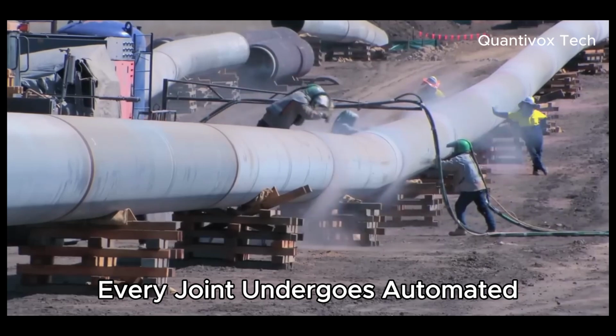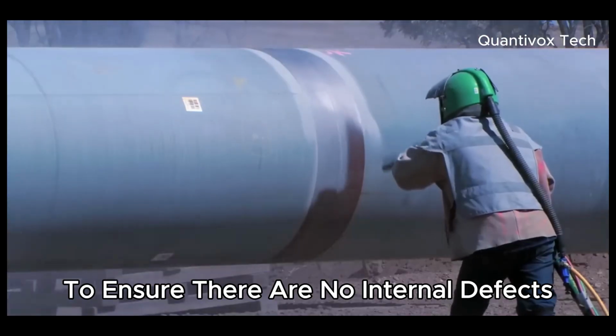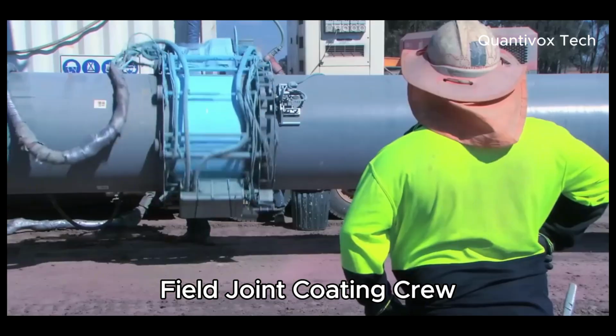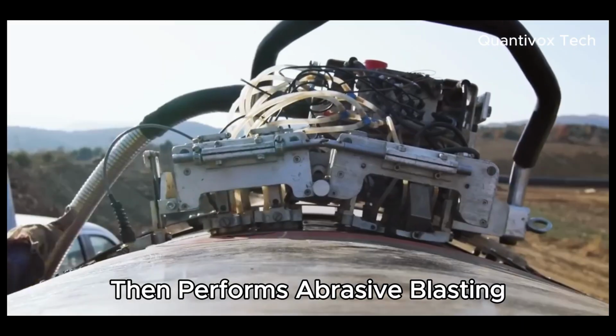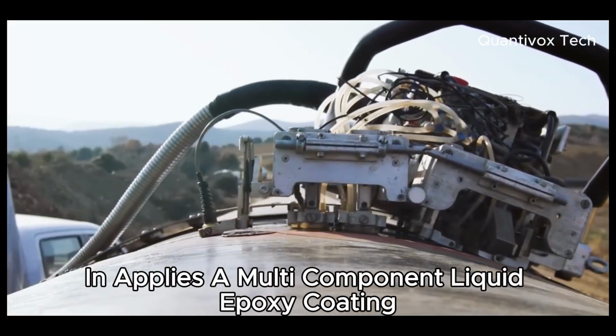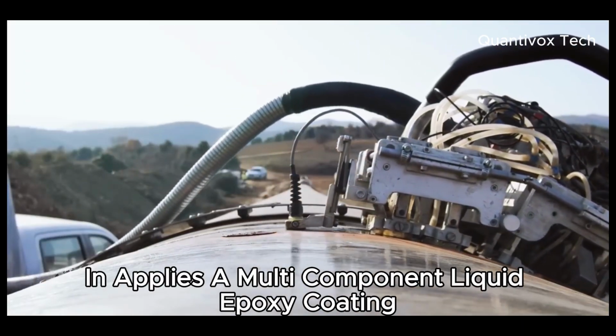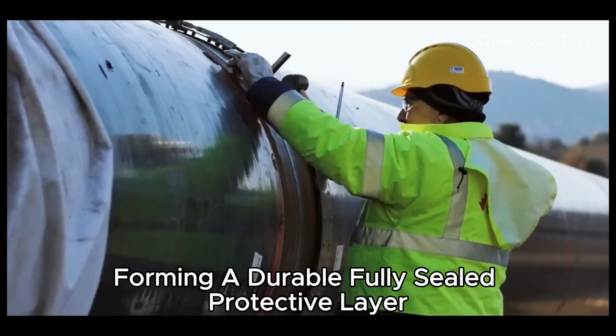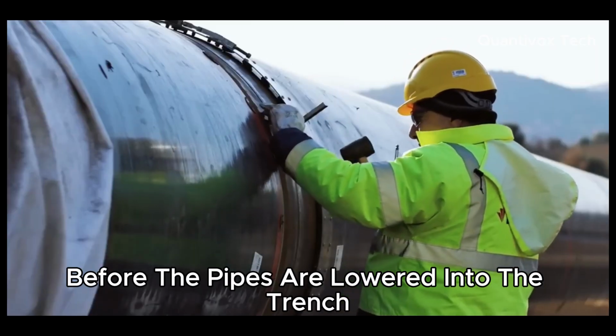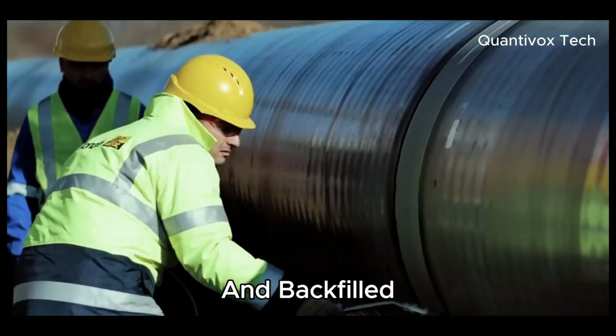As welding is finished, every joint undergoes automated ultrasonic inspection to ensure there are no internal defects. A field joint coating crew then performs abrasive blasting to clean the surface and applies a multi-component liquid epoxy coating, forming a durable, fully sealed protective layer before the pipes are lowered into the trench and backfilled.